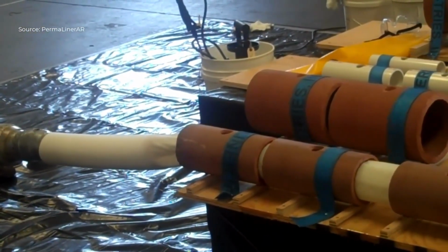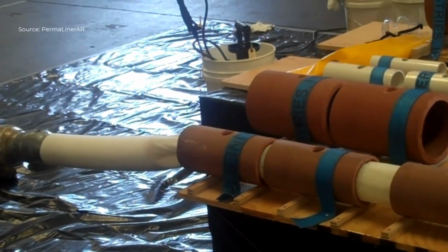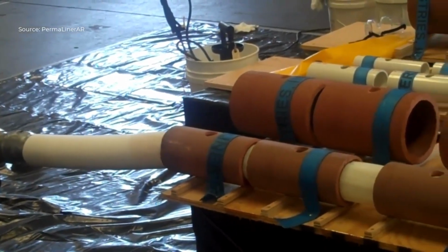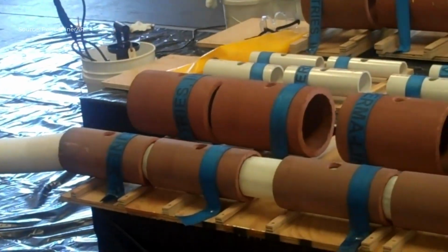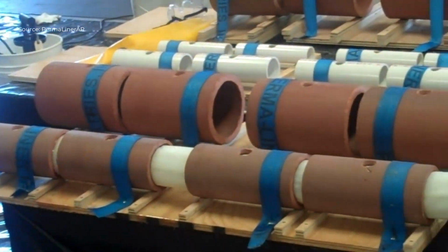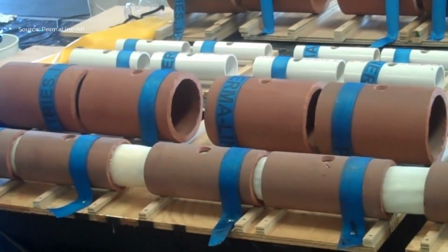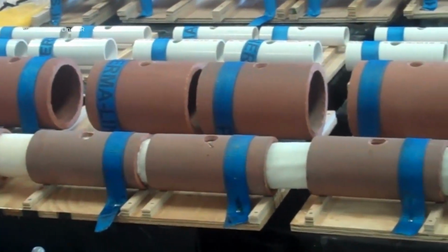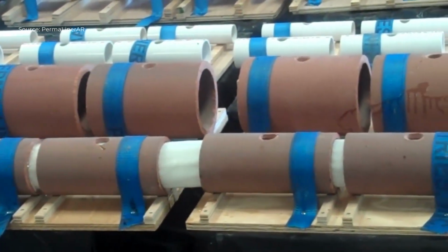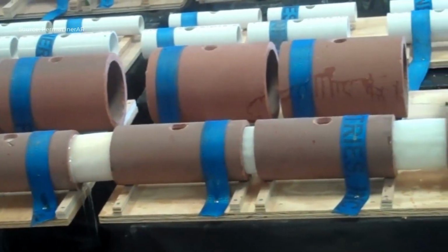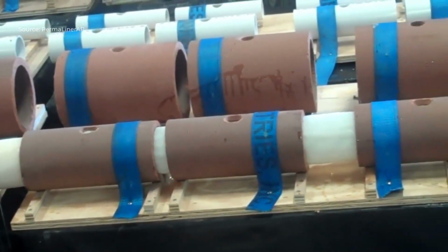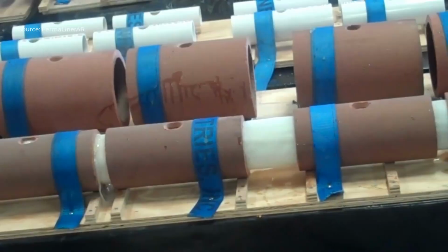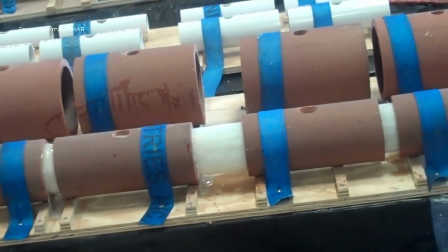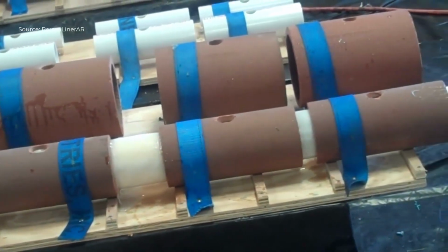The curing phase itself takes approximately 3 hours at ambient temperature. During this period, the epoxy resin undergoes chemical cross-linking, transforming from a liquid mixture into a hard, structural material. Because the epoxy is a 100% solids formulation, there is no shrinkage, and the final product retains a perfect fit. Thus, once curing is completed, the liner has become a strong, seamless pipe within the existing pipe.